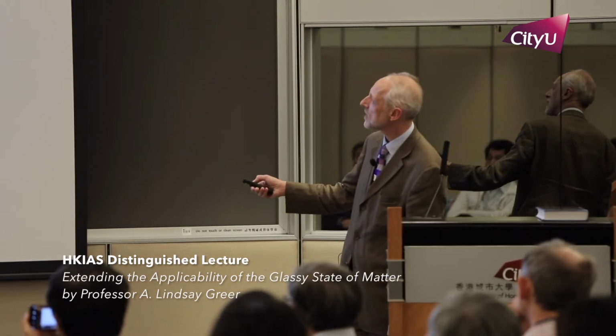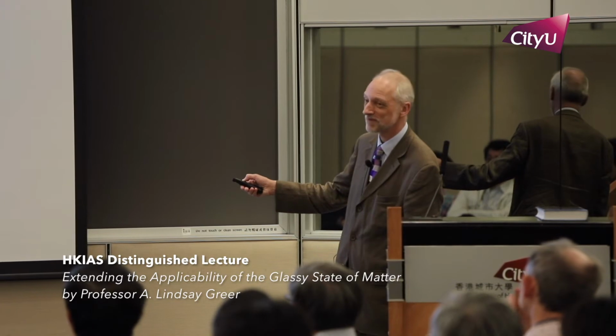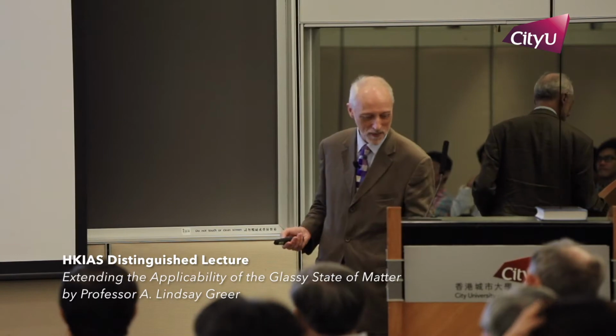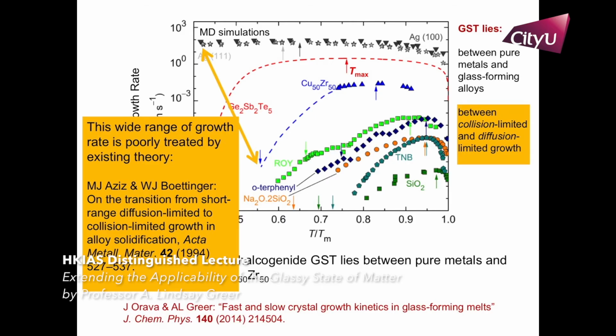But where does this sit? It sits between a classic metallic glass and a simulated pure metal. And there's many orders of magnitude in crystal growth rate there. And it's quite embarrassing for metallurgists that something so simple as crystallizing a metal is essentially a gap in existing theory. This is extremely badly understood, if at all. So there's work for us to do.